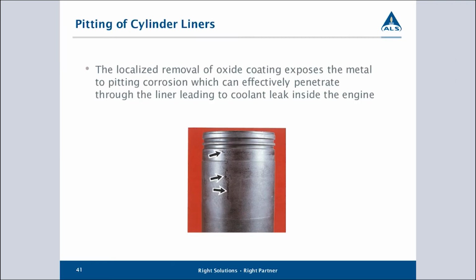So here we have an example. You can see that this pitting is occurring in a vertical line, and that would tend to suggest it's flow related. Most likely that is the leading edge of the flow reaching the cylinder. But the fact that it's also towards the top of the cylinder also suggests that vibration is playing a role in forming these pits. Now, as I said, one of the problems that tends to occur is that you get these ideal corrosion conditions in one of those bigger pits, and it starts to tunnel. It will literally drill right through the liner until you get water transferring into the inside of the cylinder from this process.